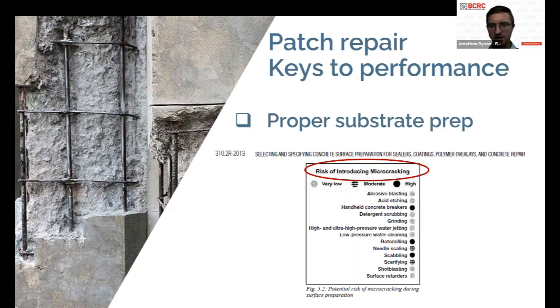There's a number of key considerations, one being proper substrate preparation. So once you've broken out the concrete, ensuring that the substrate that the patch material is going to be put on top of is sound, has a good surface roughness, etc. One of the things to consider is what is the technique used for breaking out the concrete? Because different techniques, such as mechanical breakers, hydro demolition, needle scaling, etc., have a different risk of introducing micro cracking into the surrounding concrete. And there's a really good guide, ICRI guide 310.2, which has some great detail on the risks of different techniques when it comes to concrete breakout and the risks of introducing micro cracking.